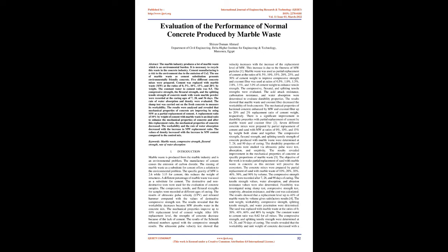The rate of water absorption and density were evaluated. The slump test was carried out on the fresh concrete to measure its workability. The results were analyzed and revealed that mechanical properties of concrete are improving by using MW as a partial replacement of cement. A replacement ratio of 10% by weight of cement with marble waste is an ideal ratio to enhance the mechanical properties of concrete, and after this replacement ratio, the mechanical properties of concrete decreased.